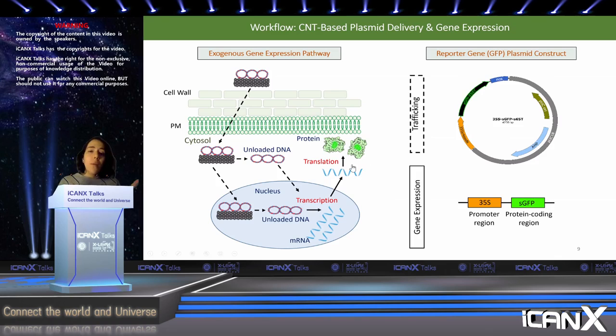Now, one question with the development of this platform is how tightly does the cargo have to be attached to the carbon nanotube? Because if it's too tightly attached, it might not be available for transcription. But if it's too loosely attached, it might detach prematurely before making it into the cell, especially while crossing the small cell wall. And so to answer this question, we developed 2 different chemistries that have different attachment strengths between the plasmid and the carbon nanotube.